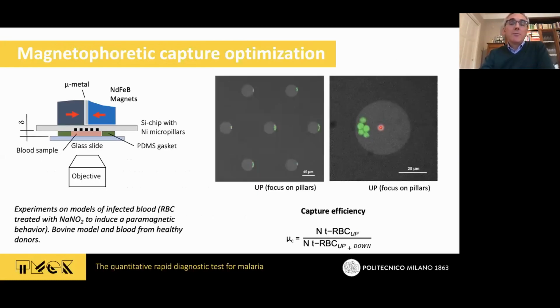So this was the first experiment that we carried out in this configuration, in order to check the capability to attract infected red blood cells. Here you see the assembly of the two magnets. Then we place this assembly directly in contact with the rear face of our chip, which is placed face down with the nickel micropillars now exposed to the blood sample, which is contained in this cell defined by this gasket in green and the glass slide. The glass slide was used in order to directly observe the motion of the particles using an inverted microscope, by staining the cells with some fluorescent molecules in order to directly see them.